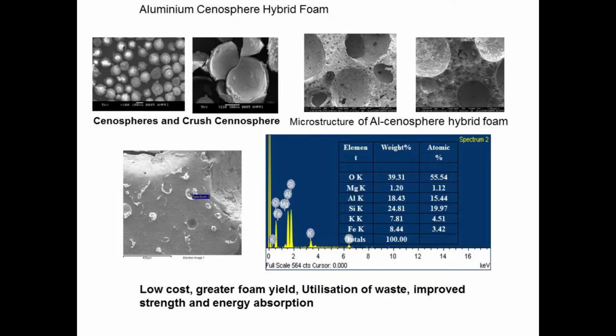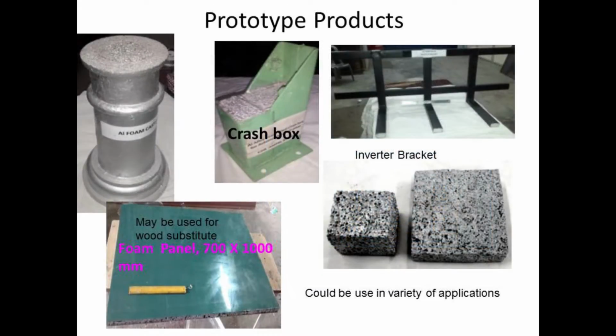Suppose when we are adding SiC as the thickening agent, we add around 1 to 1.2% of hydride. But in this case, if we use cenosphere, around 0.5 to 0.68% of hydride is sufficient. Thus, it will reduce the cost of the foam by 30 to 40%. And it can be made into any shape. If we get the crucible where we are foaming to have a particular shape, the foam can be made into any shape.